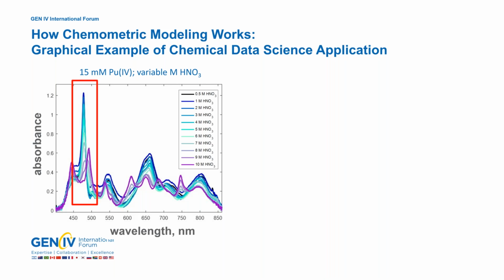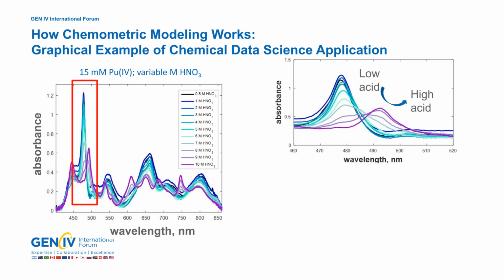So instead of using that single variate calibration curve approach, what we're going to use is multivariate technology. So we're going to use the entire wavelength range, or we're going to be using the entire fingerprint of plutonium-4. So let's talk about what that looks like. We're actually going to zoom in on that primary response band of plutonium-4, and we'll blow it up over here on the side. And just to walk you through what happens as we increase acid concentration, this primary band drops, scoots over, and then grows back in.